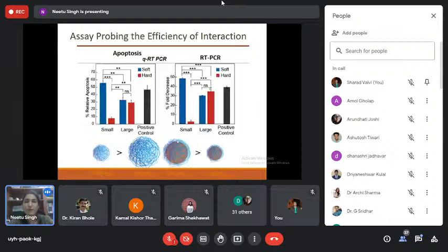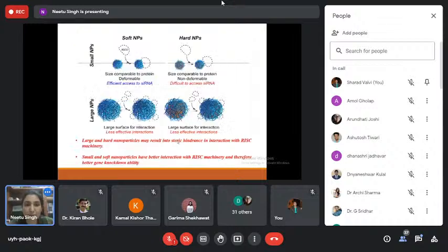Now again, we confirmed that this is the real effect, and we are actually looking at gene knockdowns. So this is the mechanism that we developed. What is happening in the soft nanoparticle is, you have your protein. It is easily interacting. It's soft, so you have a deformation of the nanoparticle and nice interaction happens. If you have a large particle, if it is soft, it can interact well. If it is hard, how is it interacting? It has more surfaces for it to interact. It actually looks at it as a local region, which we missed out when we were looking at single particle interaction. Okay, so you have a large surface for interaction.